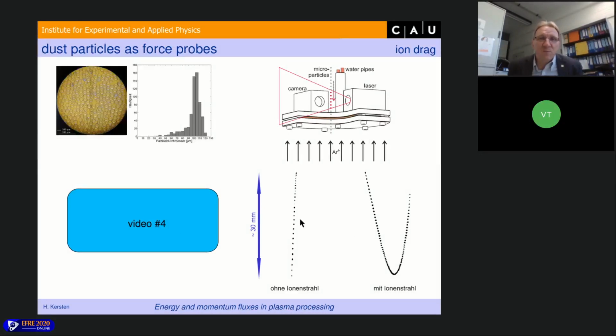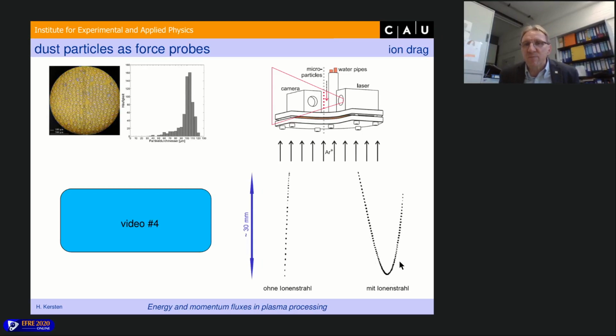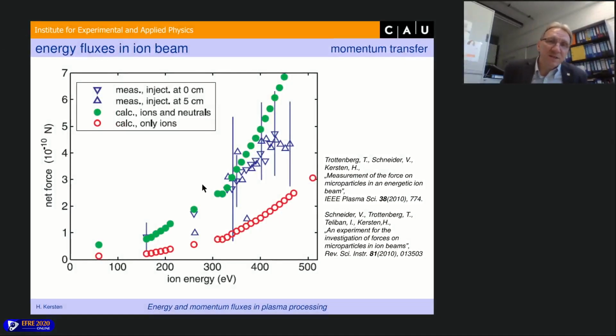Okay, and if there is no plasma, then the particles would fall down, and due to Galileo's law, they are accelerated. And if we have an ion beam against the falling particles, then the particles are decelerated, they stop, and they are accelerated back by the ion beam. And this is just the experiment we did, and we could calculate the transferred force to the dust particles, the probe particles, and we could compare these, the triangles, with our calculations from the power measurements when we include the ions and the neutrals.